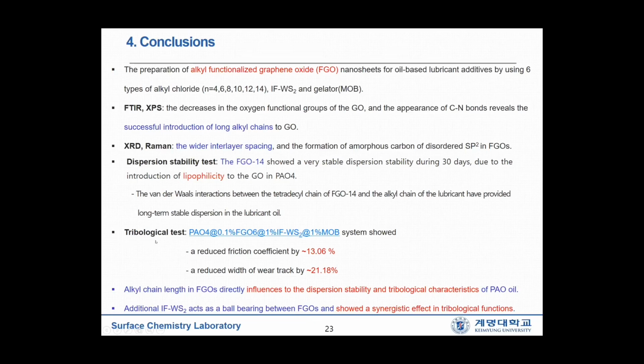Tribological test. By this test, this sample, PAO4 with 0.1% FGO6, 1% IF-WS2 and 1% MOB system, shows the best performance. This material reduced the friction coefficient by 13.06%. This material also reduced the width of wear track by 21.18%.